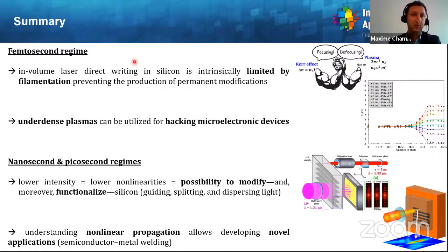In the femtosecond regime, in-volume laser direct writing in silicon is intrinsically limited by filamentation, which prevents the production of permanent modification inside the material. However, the produced underdense plasmas can be utilized for hacking microelectronic devices. And then in the nanosecond and picosecond regimes, the lower intensity leads to lower nonlinearities, and it is possible to modify and thus functionalize silicon with the inscription of optical elements inside the material for guiding, splitting, and dispersing light, for instance.